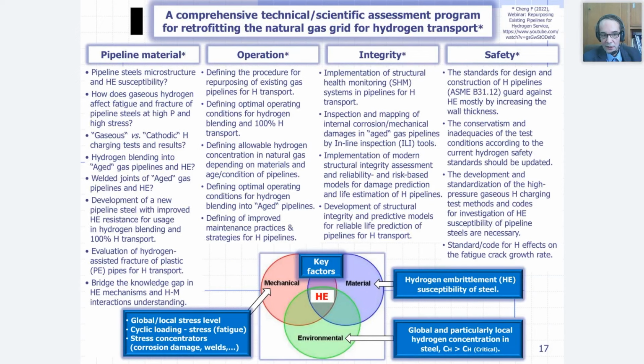What about aged pipelines and hydrogen blending allowed ratio? Next is welded joints. I already mentioned that. So we need also to develop new pipeline steels with improved hydrogen embrittlement resistance for usage in hydrogen blending and 100% hydrogen transport. We also need to evaluate the plastic pipelines made of polyethylene for hydrogen transport, particularly at lower pressure, and evaluate the hydrogen-assisted fracture of such pipelines. And finally, we need the fundamental research to bridge the knowledge gap in mechanisms of hydrogen embrittlement and the complex hydrogen materials interaction. What about operation?